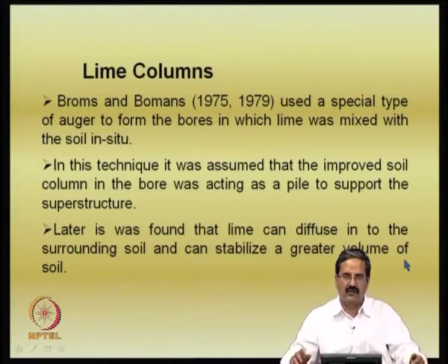People have done a lot of work on the diffusion of lime in soils, at IIT Madras, the Institute of Science and many other places. We create lime columns, then we study the concentration of cations, the calcium ions. Initially it was less, but as time goes on, the concentration of cations also increases next to the lime column.